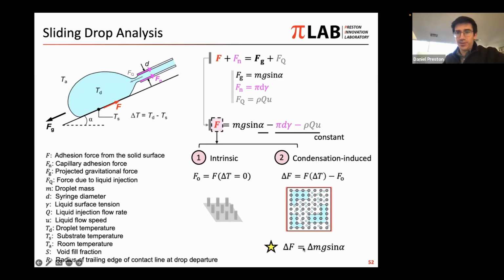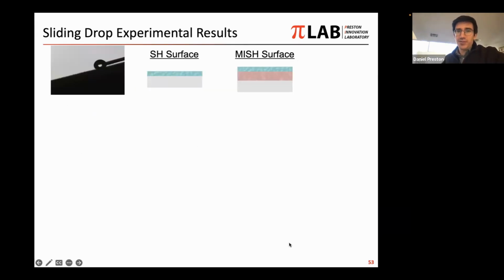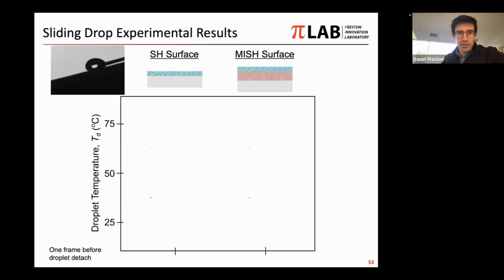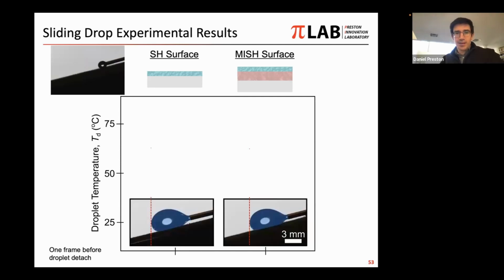Now delta F in this case should be equal to, based on the equation up here, delta m g sine alpha. Alpha is constant, so it should be basically proportional to delta m. And so we can do experiments where we look at the change in the mass of the droplets as they slide off to characterize this change in adhesion force delta F. That's why we do these experiments, and we did them both on the super hydrophobic coating only and also on the MISH surface. So we can look at these, and we basically look at the video one frame before the droplet detachment. And we find that in this case, at room temperature, they look identical.